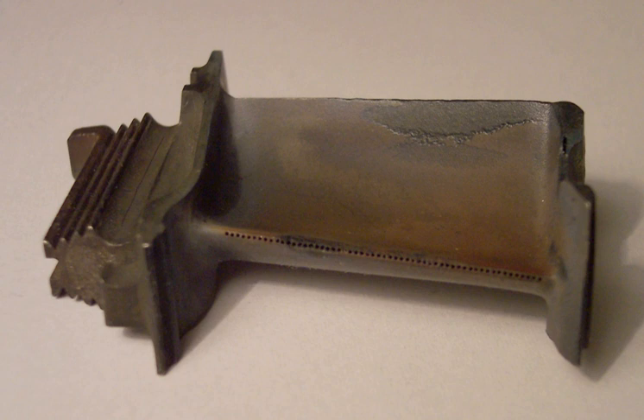Turbine blade components were forged until vacuum induction casting technologies were introduced in the 1950s. This process significantly improved cleanliness, reduced defects, and increased the strength and temperature capability of the material. Modern superalloys were developed in the 1980s. The first generation superalloys incorporated increased aluminium, titanium, tantalum, and niobium content in order to increase the gamma volume fraction in these alloys. Examples of first generation superalloys include PWA1480, René N4 and SRR99.